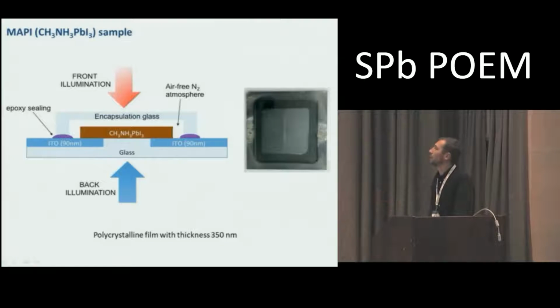So here is the photo and the picture of the samples we use in our study. We employed the material prepared in a way traditionally used for fabrication of real solar cells. Only some parts, so it is not an actual solar cell, but we just do not add additional layers here. But in principle, this sample looks like a solar cell.